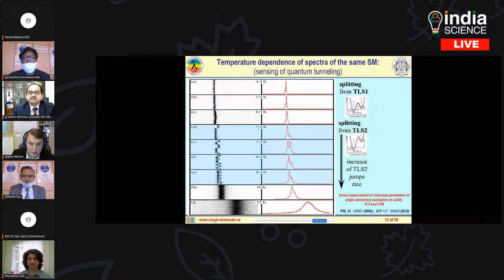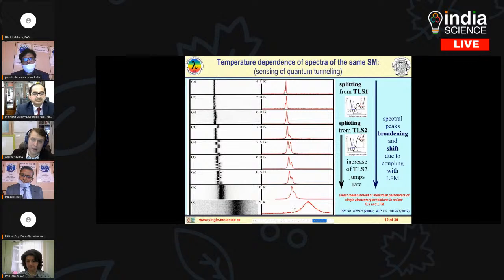So by analyzing these jumps, we can understand the temperature. So we have a very, very small temperature sensor with a size less than 1 nanometer. So we can put such an extremely small temperature sensor everywhere, into condensed matter, into a living cell, and so on. And we can reconstruct the temperature. We can find the temperature in a very small volume for different objects. Also, along the whole temperature range, you can observe spectral peak broadening and shift because of electron-phonon coupling. So we can study vibrational excitation in our sample.